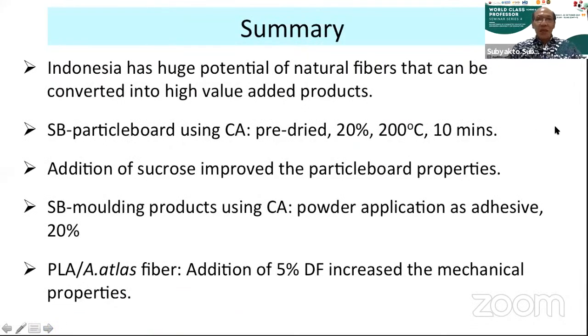I think I would like to summarize our work. So we have a huge potential of natural fibers in Indonesia. I think we can cooperate to make a collaboration research on this one. And when we make a particle board from sorghum bagasse using citric acid, we have to pre-dry it, and this is the condition: 20%, 200 degrees C, and 10 minutes. And addition of the sucrose improves the properties.